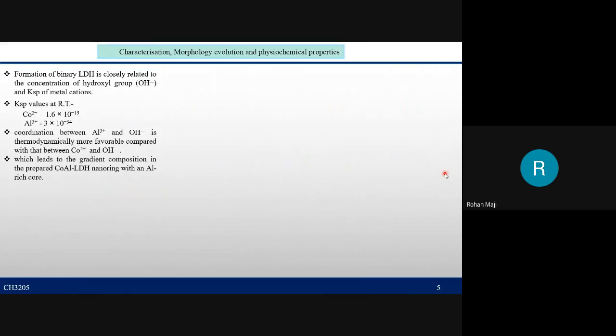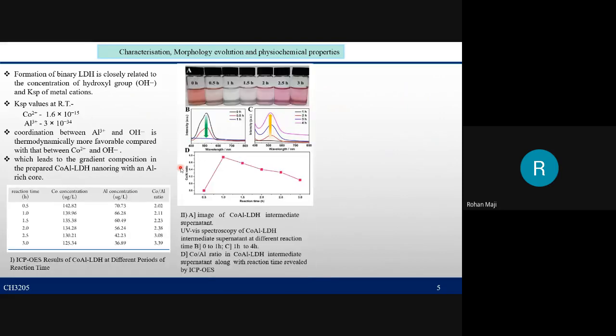So, the immediate next question comes: which metal cation resides on the inner side, that is at the boundary of the pore and nanopore, and which cation lies towards the edges. From Ksp data, we can see that aluminum has lower Ksp. So the coordination between aluminum and OH- is thermodynamically more favorable compared to cobalt 2+ and OH-. So there should be a gradient composition with an aluminum 3+ rich core. Further characterization using UV, ICP-OES, TEM also supports that.